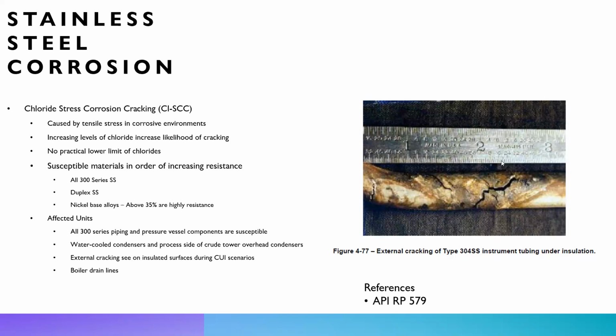You can even see it, like in this picture, on the externals with the CUI scenario, where the chlorides in the insulation, when they have a CUI, can penetrate the metal and lead to a catastrophic event because you can't see it, because it's under the insulation. So definitely, I would say this is what I see the most and what we repair the most, and it's pretty frequent, to tell you the truth.